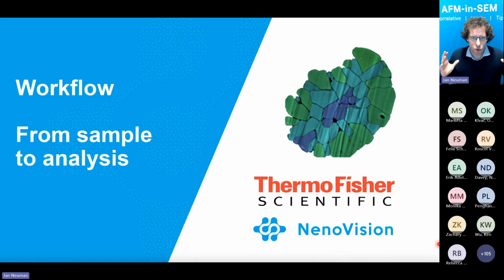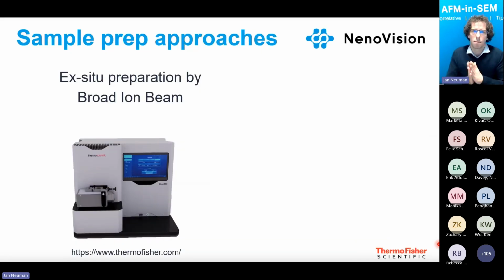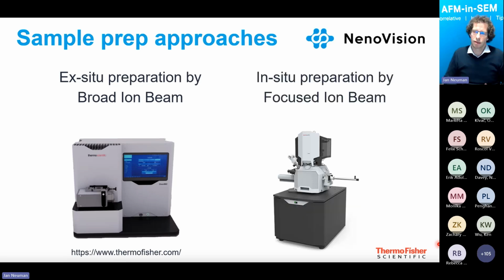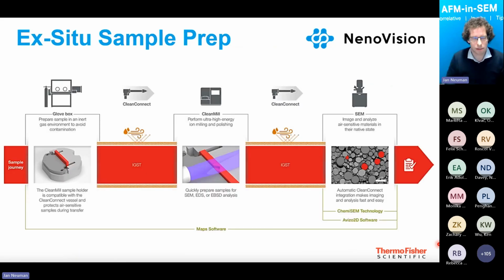Here I would like to demonstrate the workflow for sample analysis. And thanks a lot to Thermo Fisher Company, because for more than a year we have been working together to provide such a solution. Basically, I would like to introduce two ways to prepare samples properly. The first, which we call ex situ sample preparation, uses broad ion beam milling to make the cross section and polish the surface. Another approach, which we call in situ sample preparation, uses a focused ion beam directly installed inside the SEM. I will briefly describe both of them.